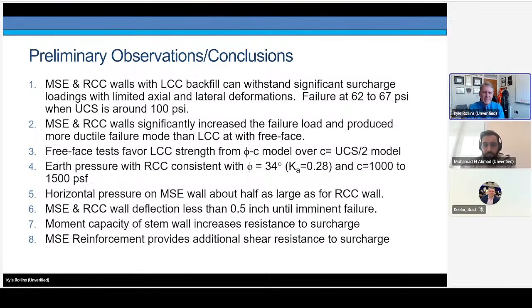If we look at the free face failure situation, the LCC strength was best predicted using a C-phi model rather than taking half of the unconfined compressive strength. There's a possibility that we might be able to use the shear strength of concrete for unreinforced conditions. But using UCS over 2 didn't work very well. The earth pressure with the RCC was consistent with what we'd expect if we used Rankine theory with a cohesion of 1,000 to 1,500 PSF, for example.